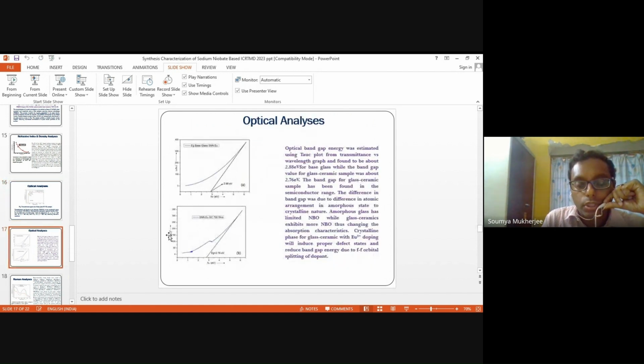Moreover, the band gap energy calculations of the base glass and the glass ceramic systems have been compared, and it is noted the base glass has a band gap of 2.88, while in the case of the glass ceramic sample it is 2.76. The difference is mainly due to the change from amorphous to crystalline nature. In amorphous, the non-bridging oxygen is limited, while in the glass ceramic, due to the more crystalline order, the non-bridging oxygen becomes more prominent, and as a result these changes come up. Moreover, europium 3+, which is utilized as a dopant, will also induce some defect states and some 4f orbital splitting, and that will also have some impact on the band gap change.